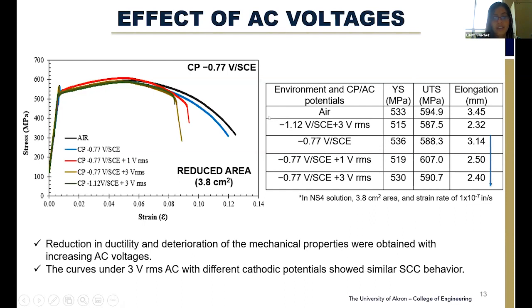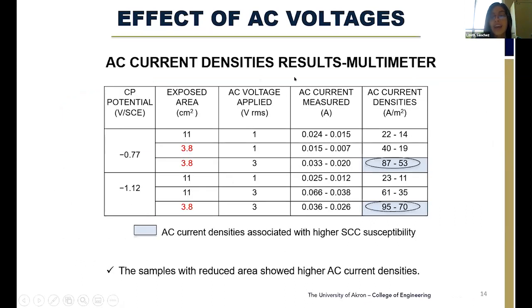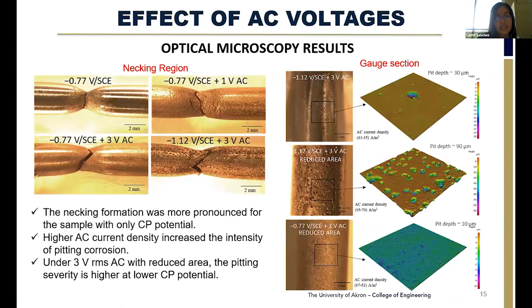In addition to that, here I'll show you the AC current densities that we measured during the test with a multimeter, and we see how the AC current density is higher for the sample with the small exposed area and with the higher AC voltage. So after that, we again analyzed the fracture mode in the optical microscope.